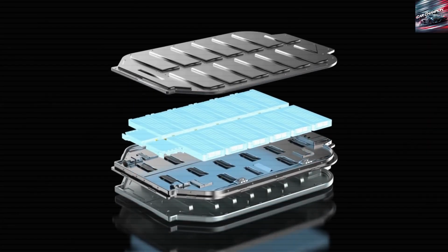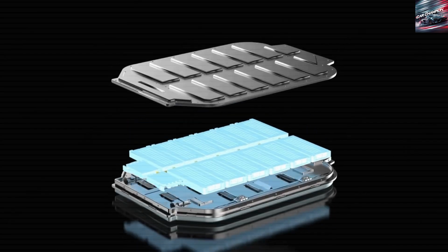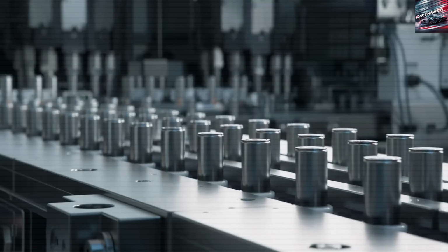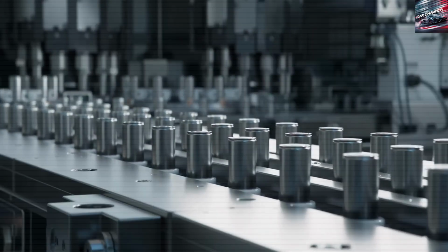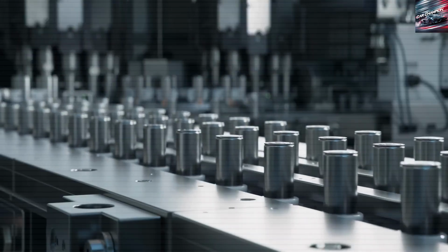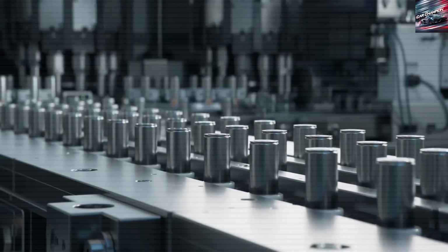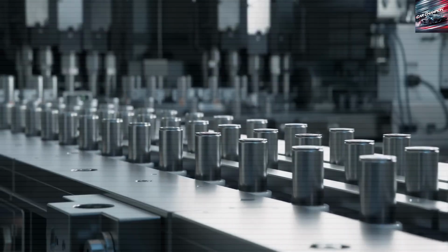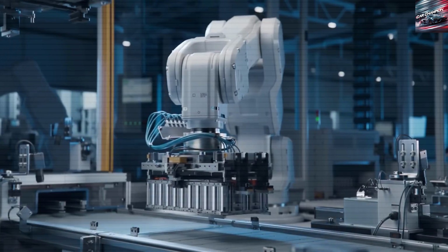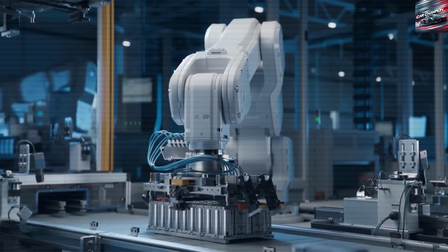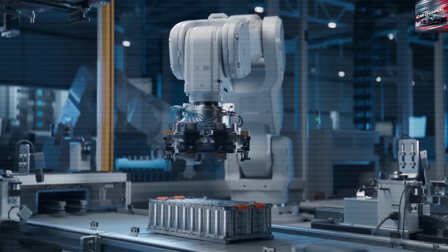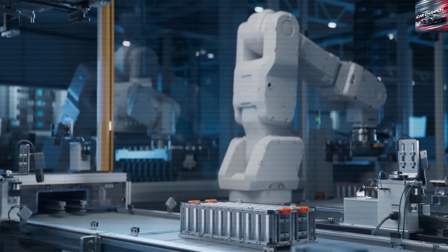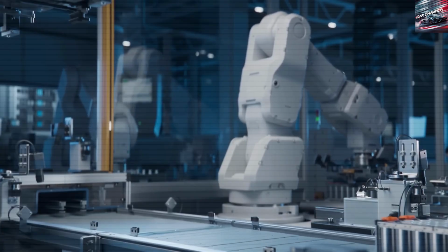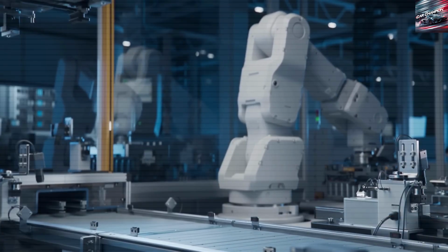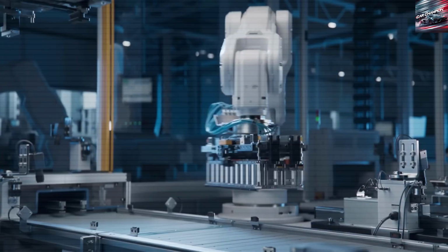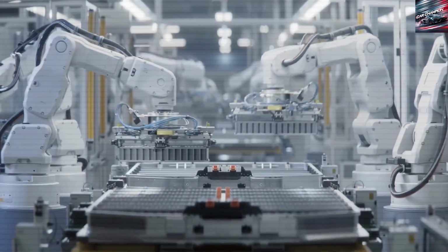To achieve these results, BYD has upgraded both electrode materials and the solid electrolyte. They reportedly use an ultra-thin composite oxide solid electrolyte and high-capacity anode and cathode materials to boost charging and discharging rates. For context, the current BYD Seal with an 80 kilowatt-hour Blade battery offers about 373 miles of range. With a new solid-state battery, that same 80 kilowatt-hours could provide up to 870 miles. A smaller 60 kilowatt-hour battery could still give around 621 miles.